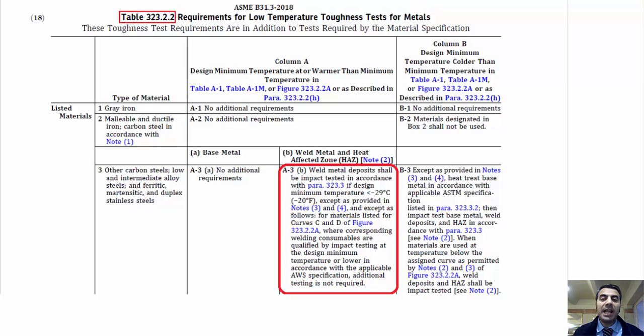In this case, the base metal meets A3b, and the weld metal deposit and heat-affected zone shall be impact tested if the design minimum temperature is less than minus 29 degrees Celsius or minus 20 degrees Fahrenheit.